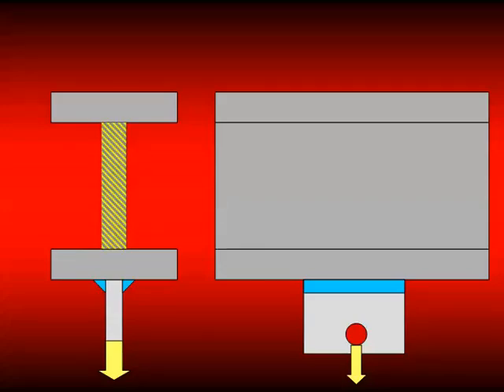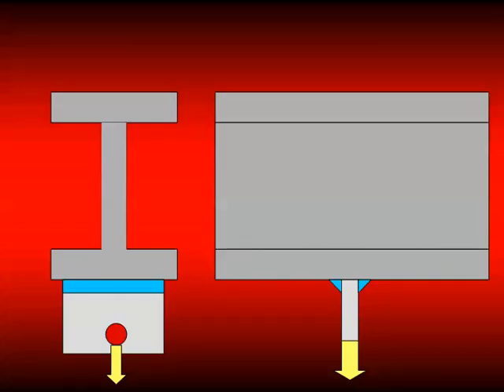But what if we rotate that lug 90 degrees? And I trust that you can see that this is a markedly different situation. Because now we no longer have the same load path going directly into the web. It needs to transfer through the weld into the flange and then somehow get concentrated into the web of the section. And so now our weld is no longer uniformly loaded along its entire length.